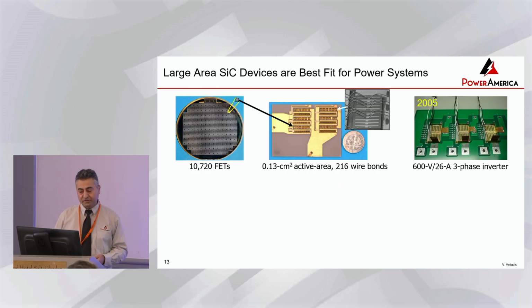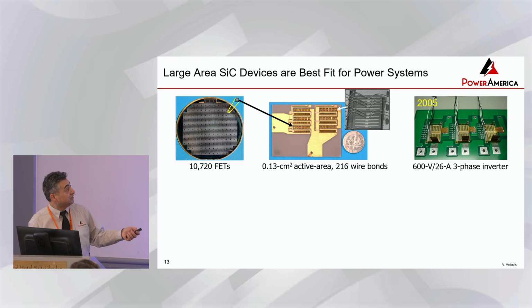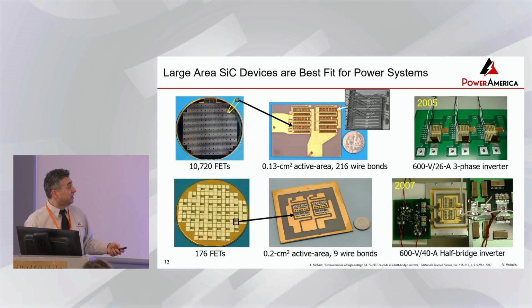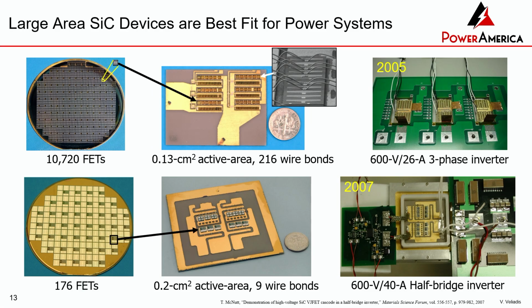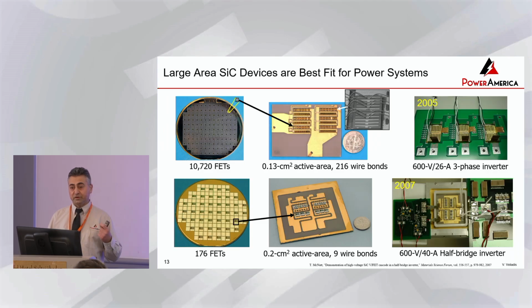Okay, so why do we need large devices? Here is a 3-phase inverter back from 2005. And you can see that to get 0.13 centimeters of active area, I needed 216 wire bonds. And a device would fail. I had to look under the microscope to find the burned area. As soon as I increased the size, as you can see here, then instead of needing 216 wires, I only need 9 wire bonds to get more area connected, and then build a half-bridge inverter. So basically, large area silicon carbide devices, wide-bandgap devices are absolutely needed in order to get to the power systems, right? Because paralleling a number of devices is very, very problematic. So large area, big devices, those help compete with silicon.